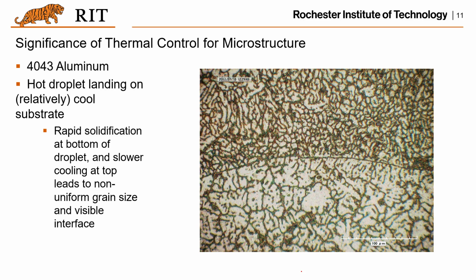Another very interesting aspect is the thermal control for the microstructure. As you can see, if we use this 4043 aluminum material, and the thermal control is not good, meaning the substrate is at a cooler temperature than the droplet, what happens is something like this. You can see there's a very clear distinction between each of the layers because there's no melting during the process. That means the first layer and the second layer will not be diffused together, which is undesired, right? You don't want to have the printed part in different segments instead of a whole unit part, right?